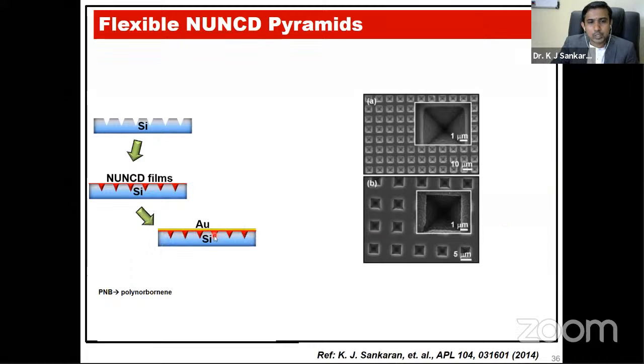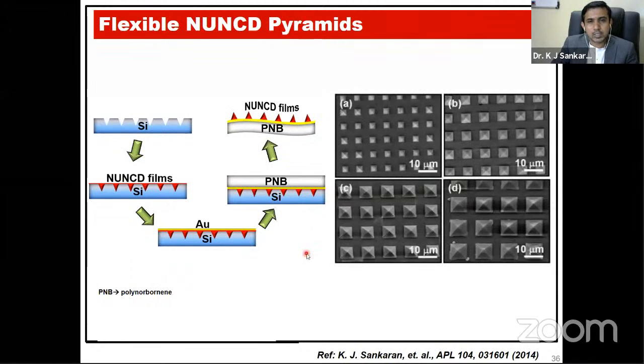And then we used a gold layer on these NUNCD films. After coating the gold, we used a polymer called polynorbornene. So we spin-coated this polynorbornene on the NUNCD films coated on these silicon pyramids. Then we reverse this by etching out the silicon. This polynorbornene will be flexible, and the NUNCD pyramids will sit on the gold film between the diamond and the polynorbornene. So we can achieve a flexible nature of NUNCD pyramids on this polynorbornene.